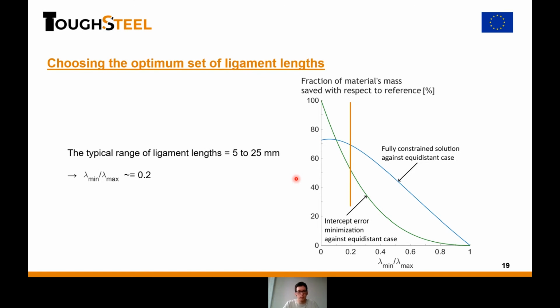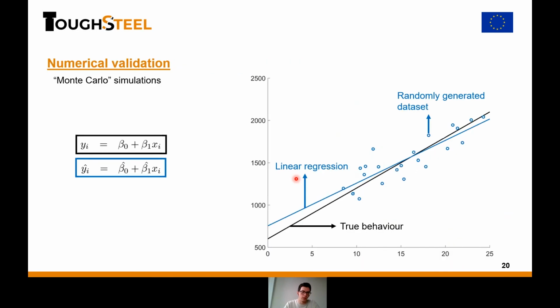But this is a bit of a statistical and mathematical model. How do I validate this model? First, I try to validate it numerically, doing a type of Monte Carlo simulation where I set the true behavior, which would be linear. So I would know these two parameters, beta 0 and beta 1. Then from this, I would generate a random dataset with different strategies, either with more samples with lower ligament lengths and fewer samples with larger ligament lengths, and then make a linear regression from this randomly generated set. This would be in blue, and then I would compare the estimator to the true value.